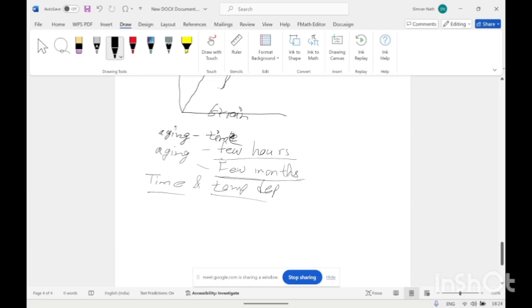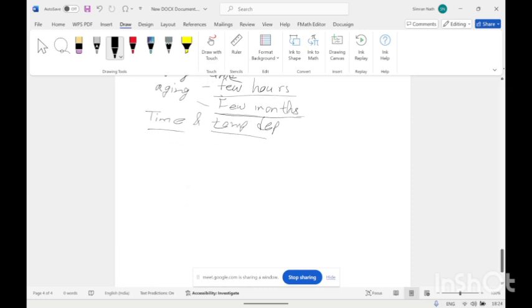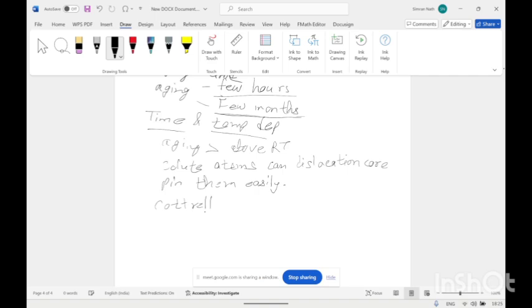And the temperature effect on the yield strength is, if the aging is at an elevated temperature, means above room temperature, the solute atoms can easily diffuse to the dislocation core and pin them easily. So there is one Cottrell-Bilby theory which is used to explain the strain aging behavior in the aluminum alloys.